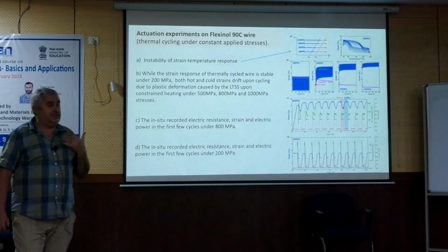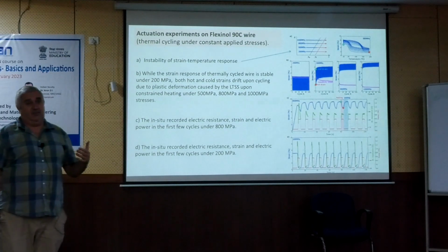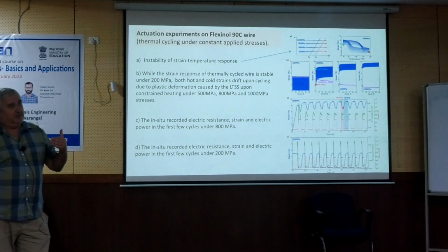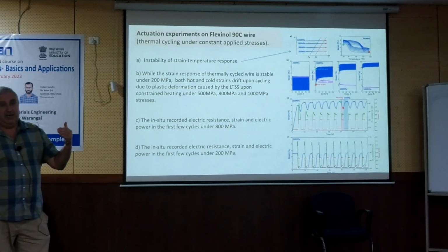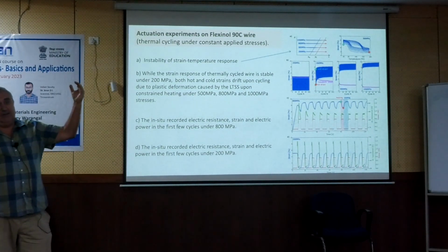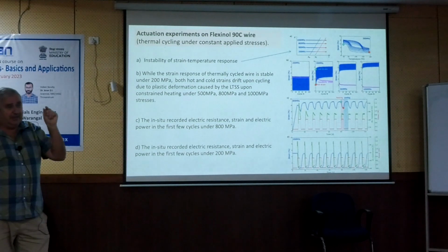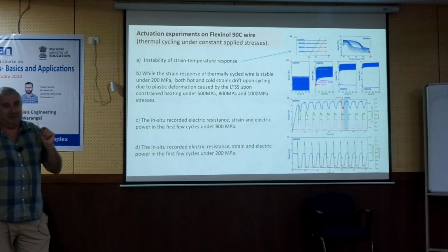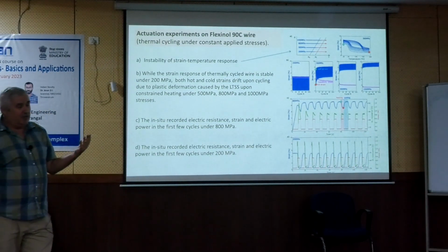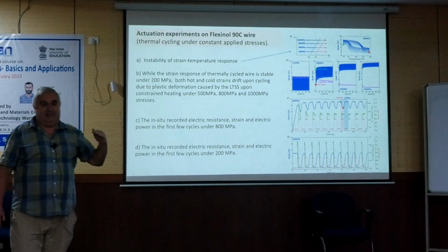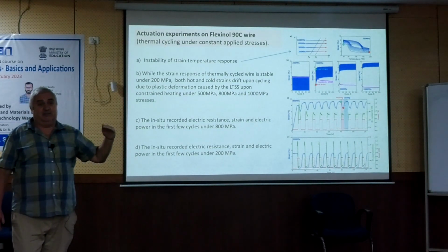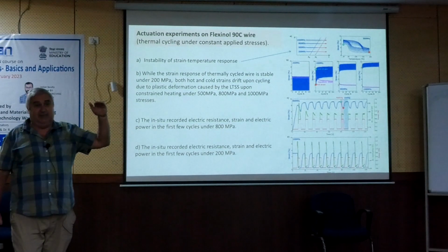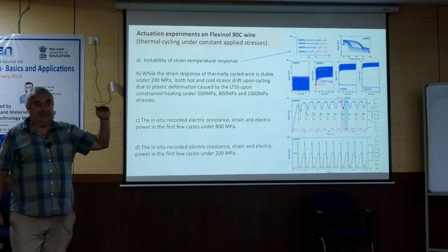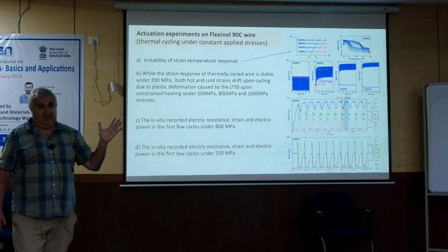What in my understanding is exciting is the trend to develop high temperature shape memory alloys. You have seen ceramics can work around 1000, but with ceramics, the responses are very, very limited. The beauty of shape memory alloy is that this mechanism, which we utilize around room temperature up to 100 Celsius, can be extended up to 500 Celsius.